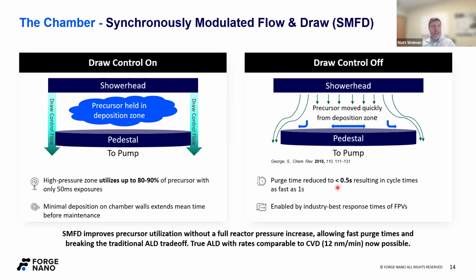So when you put all that together, we can get deposition rates for ALD that are above 10, sometimes 12 nanometers a minute. Now to kind of level set that, there are some ALD processes that can get close, but typical ALD processes for like silica or hafnia, they live in the sub-nanometer per minute range. So it is quite unique.